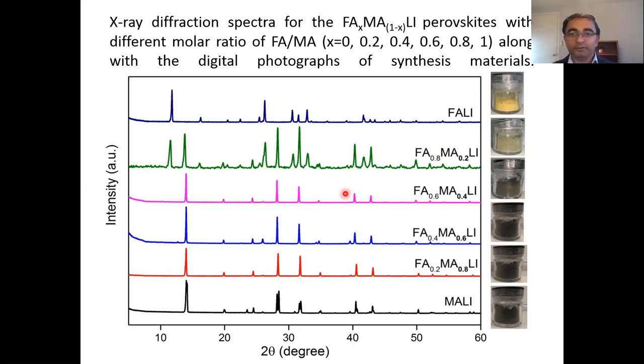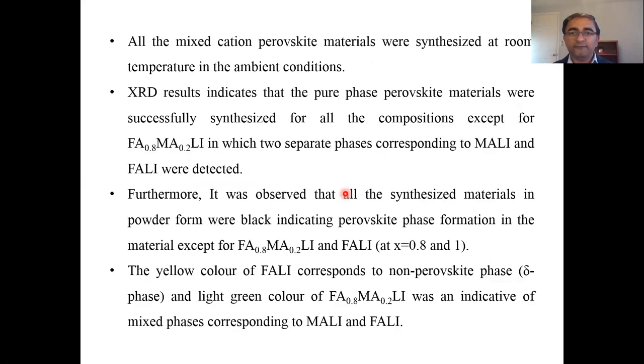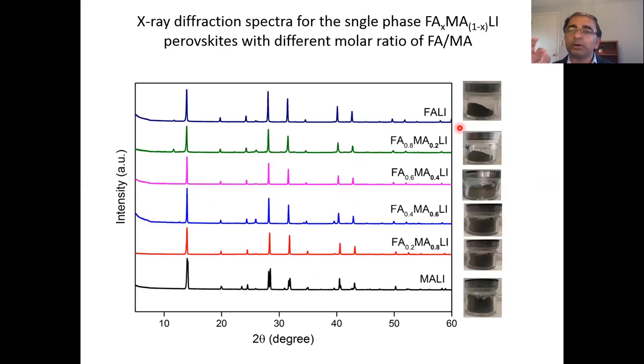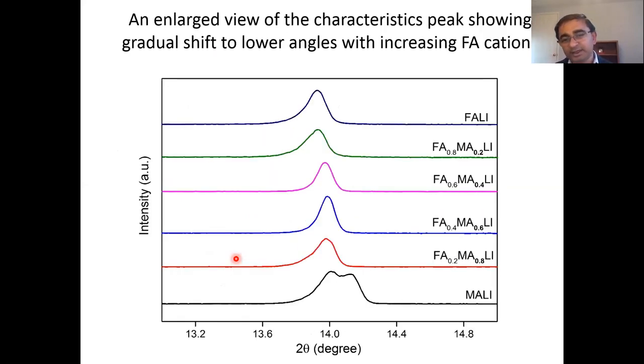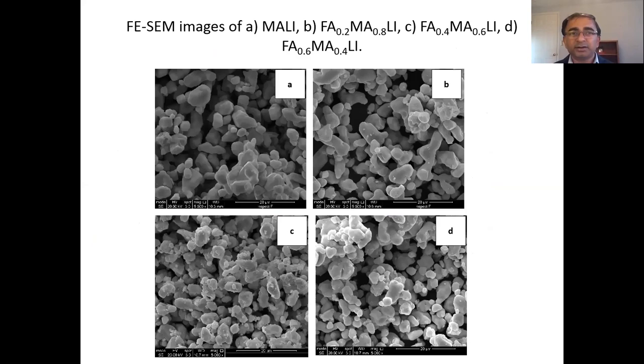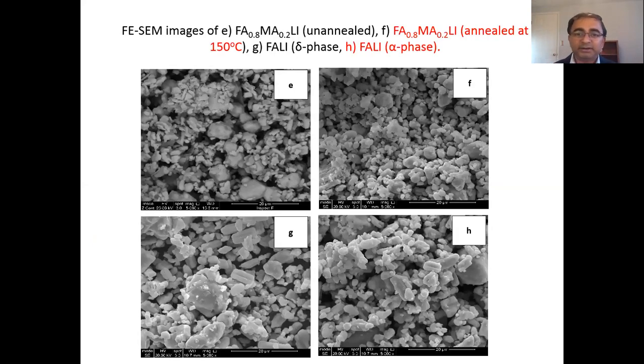So what I've done is that we have heated that material at a particular temperature for a particular time, simple heating in an oven, nothing else. And I got all the perovskite phase for the whole range, you can see from here. All are crystalline. This is the XRD of this, and this is the beauty. We are successful in making the whole range, and we are successful in tuning the whole range from MALI to FALI. You can see from here the shift of peaks, a very slight shift, because of this FA inclusion. And this is a powder FESEM. You can see all are of the same nano-sized material.